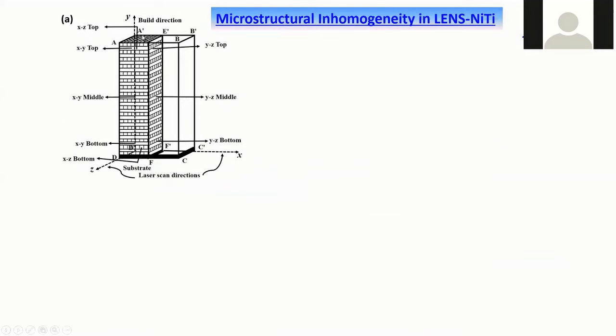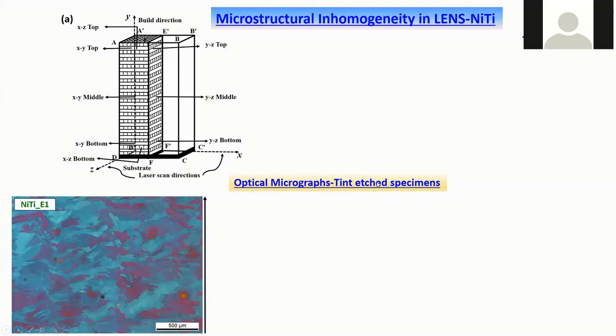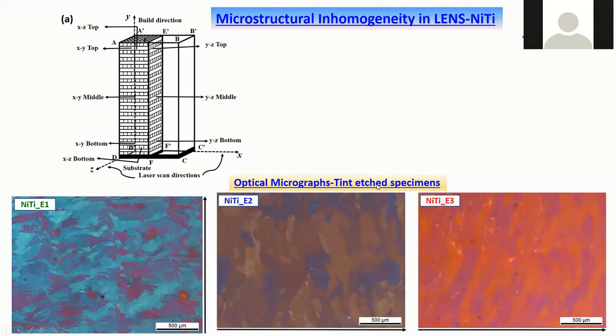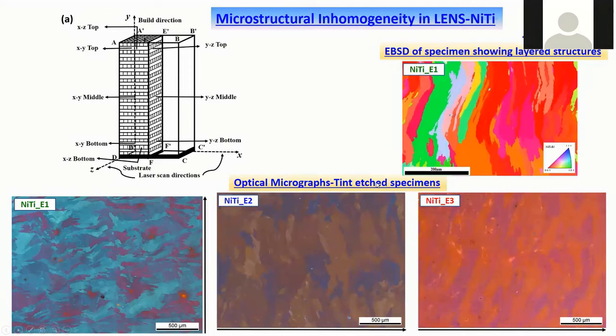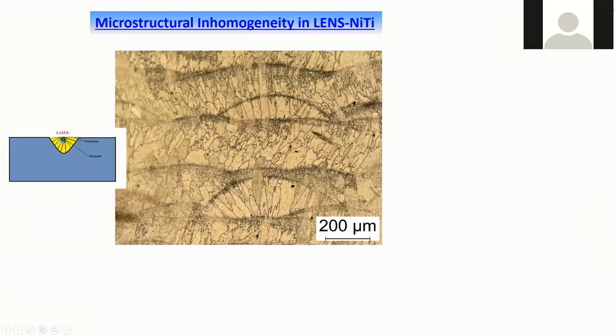Okay, now this is the schematic of the product. We did a detailed microstructural investigation at different sections from the top, middle, bottom, at different planes, XY, YZ, etc. And we have seen that the microstructure is actually quite different. We still can find the signatures of the layer by layer process itself. There's an EBSD diagram and these are the optical micrographs. You can see that these layered structures are very much clear. And if you look into the details, we can see